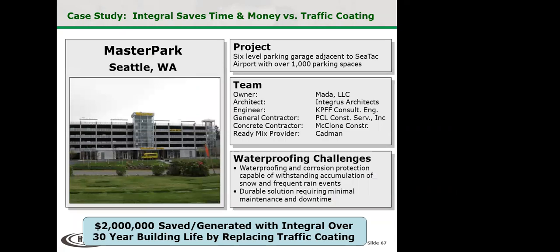Yeah, and then just a side note on that one, those were immersed in a saltwater solution so that you could see how it's going to penetrate into the concrete. This is an example of a parking structure where they opted to go with a hydrophobic admixture for their protection, for both waterproofing and corrosion. They independently calculated that they were saving about $2 million over the lifespan of this parking structure by not having to use coatings and sealers and reapply those over time, plus the lost revenue of the shutdown time.